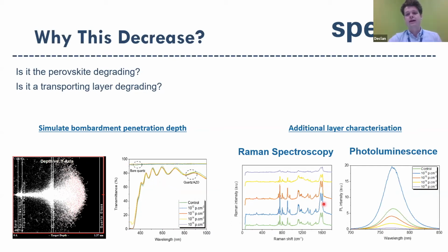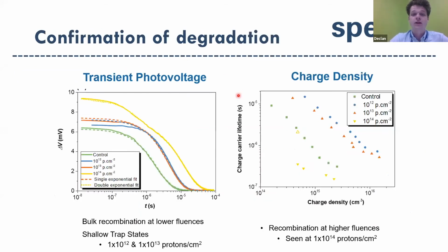We then looked at additional layer characterizations, starting with the spiro layer. We did Raman spectroscopy and photoluminescence measurements and found that as you increase the proton fluence, the PL drops and the Raman signal for the spiro decreases. So there is obviously an issue with the spiro, and we needed to confirm this.